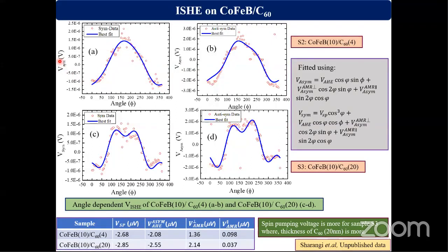So this is V symmetric versus angle, and this is V antisymmetric versus angle for cobalt iron boron C60 4 nanometer, and this is for cobalt iron boron C60 20 nanometer. We have fitted the data using these two equations. From the fitting, we get that the spin pumping voltage for cobalt iron boron C60 4 nanometer is minus 2.68 microvolt, and for C60 having 20 nanometer is minus 2.85 microvolt.